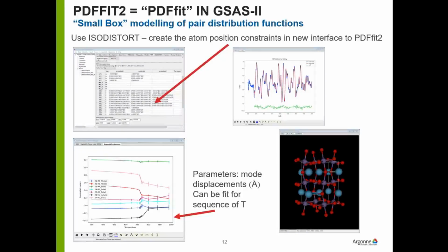go. So in this particular case, this is lanthanum manganese oxide. It's a perovskite, and it looks like that. And so the question is, if you begin with the high symmetry version of this, which is tetragonal, something like that, and this winds up being orthorhombic, how did it get there through a phase transition? And you can do that by working out what these mode displacements are and simply watch them as a function of temperature. See what they do.